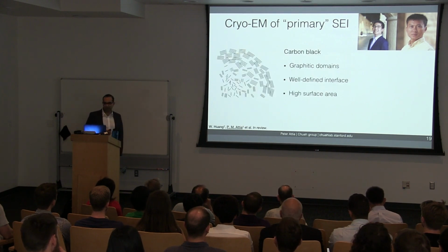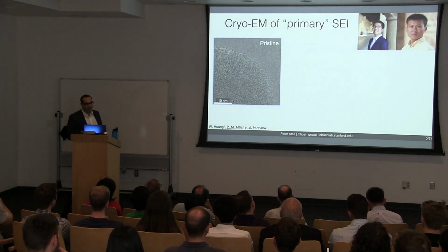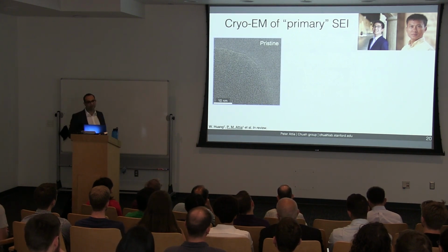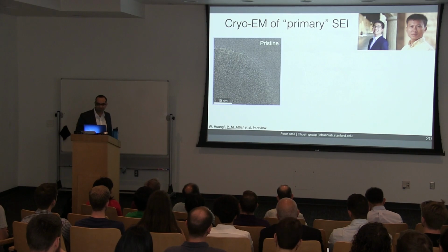Just to rehash, the key features of carbon black for imaging are its well-defined interface and its high surface area. So we look at pristine carbon black via Cryo-EM. It has this nice, well-defined interface with nothing on it. I just want to emphasize here that the thin lines that we see in the particle are atomic planes of carbon, which to me is pretty remarkable in its own right.